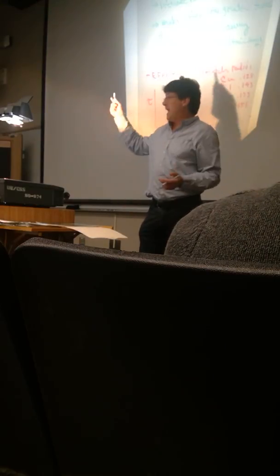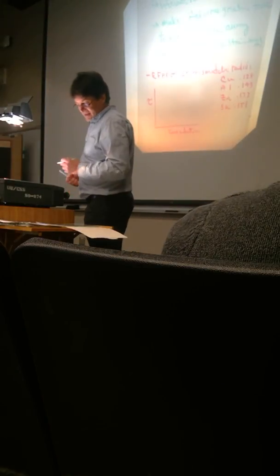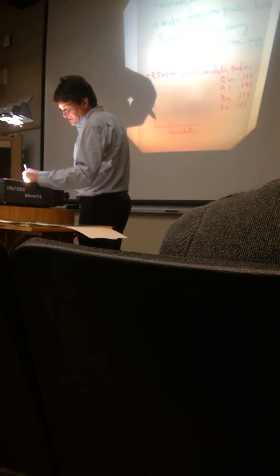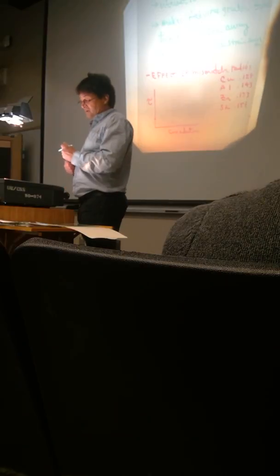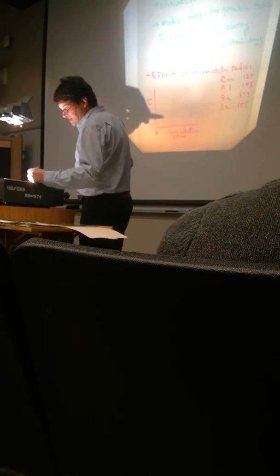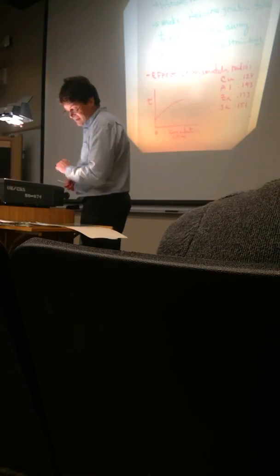So we're starting with a copper matrix, and we're going to add impurities. How is that going to affect our tau? So we know we have some intrinsic tau for pure copper, concentration 0, and C increases this way. So we already looked at zinc, and we know that zinc sort of did this, right? Okay, so the mismatch between copper and zinc is the delta R there, 0.005. We look at aluminum.